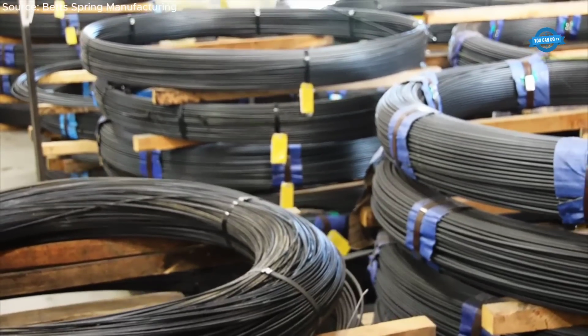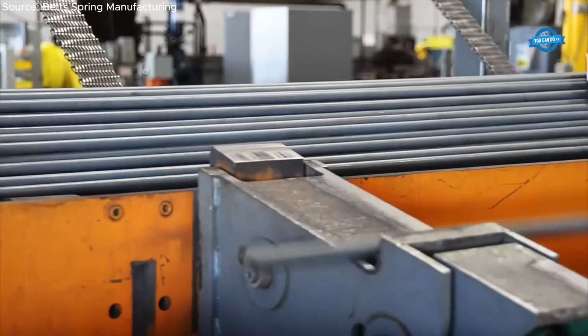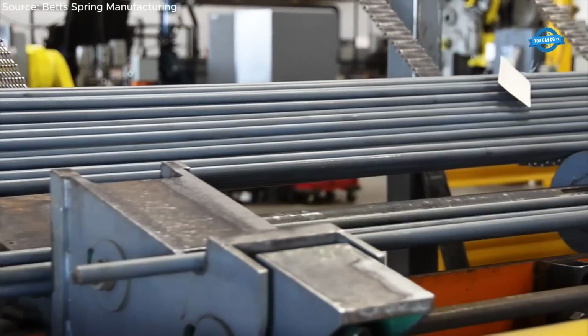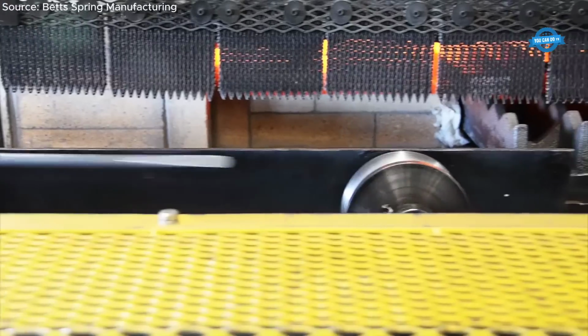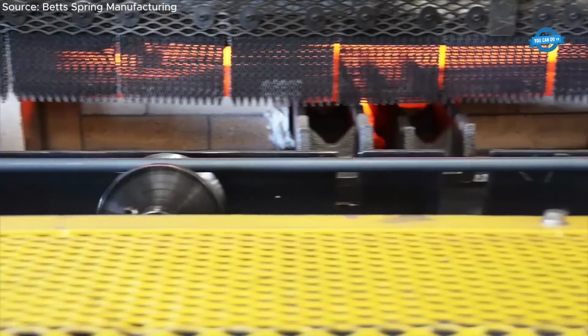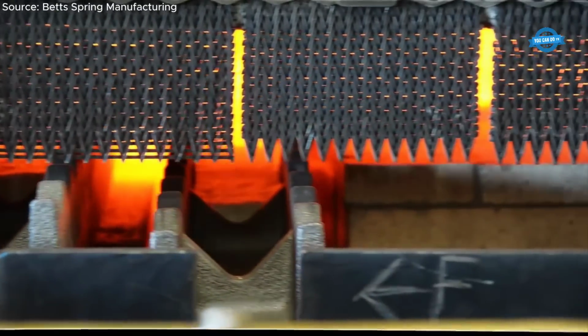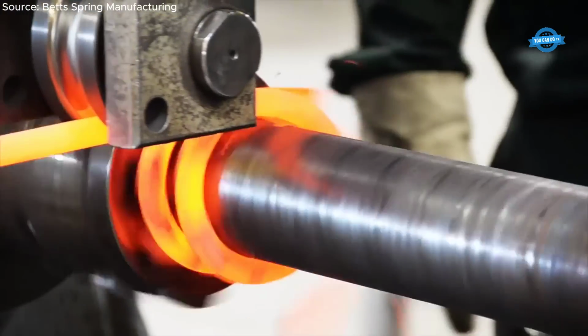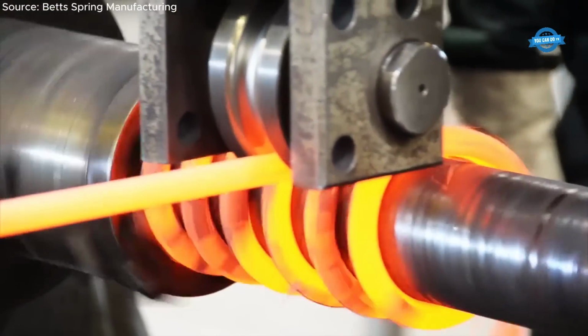Betts Spring Manufacturing employs distinct processes for crafting springs. Cold winding begins with pre-tempered material, pulled through rollers and fulcrum pins, then coiled around a precision ground arbor, using high-tensile chrome silicon for lightweight springs with diameters from 1/8 to 5/8 inch.